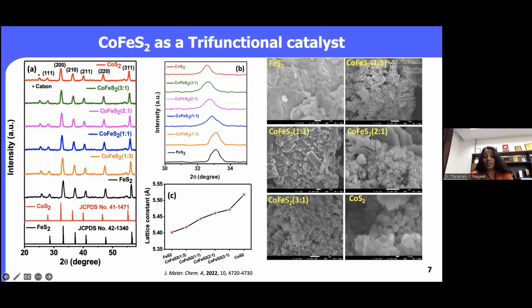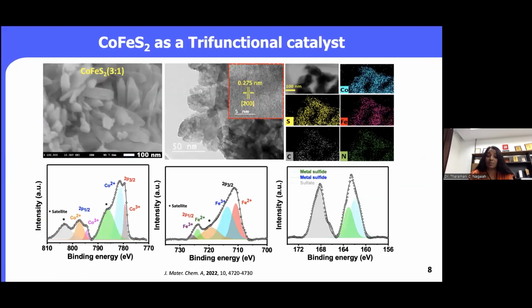And here we are varying the ratio between cobalt and iron to get the maximum efficiency with respect to the multifunctional activity. For the cobalt iron sulfide with a 3:1 ratio, we found a grain-like structure. TEM was used to understand the in-depth morphology, which confirmed that this grain-like structure is due to the agglomeration of porous nanoglobules. And the diffraction data is in correlation with the XRD data.